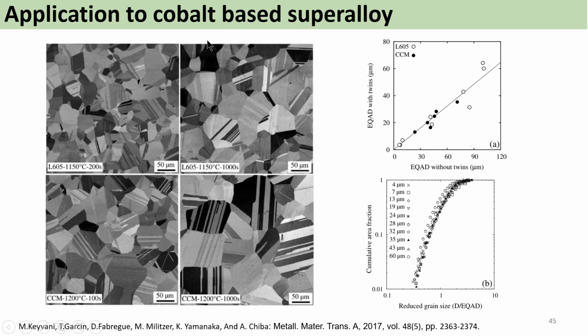So, remaining with superalloys, we now have cobalt-based superalloys, where we have done an analogous type of study. Those alloys are very important in the medical field, where they are used for implants. And again, it's very important to control the grain structure in those alloys, because it controls their ductility and strength. You can see here the microstructure is composed of equiaxed grains, which contain twins, which are annealing twins, and those twins are typical for those alloys.